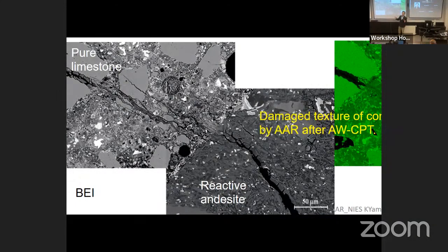So that's another possibility. Gel formed in the aggregate, if the gel is highly viscous, it is difficult for this kind of gel to move in cement paste because the pore structure is so dense. So viscous material cannot pass through this one. Then expansive pressure is stored. But another question is why at higher temperature the crack passes through and why at lower temperature an onion skin crack is formed. But this difference can be reproduced by some mechanical simulation.